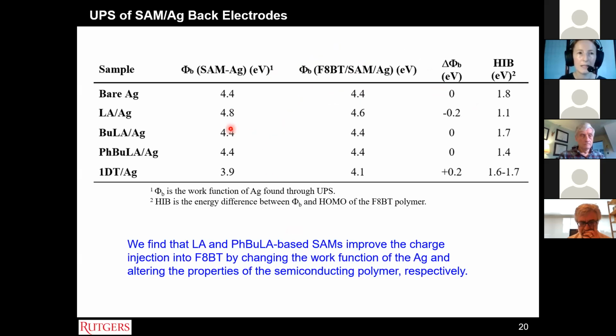We carried out UPS, ultraviolet photoelectron spectroscopy, to further confirm whether this improvement was due to a work function change or a morphology change of the polymer. You can see for the lipoic acid on silver that there is a lowering of the hole injection barrier. And for the other phenylbutyl lipoic acid case, there is no change in the work function. So we hypothesized the improvement that we saw with this particular compound was due to a better interaction with the semiconducting polymer because of the aromatic group at the end of that compound.